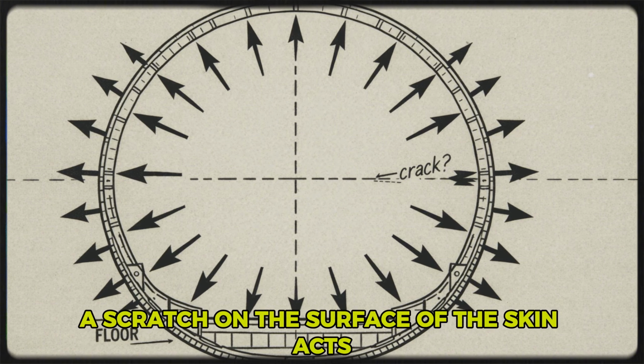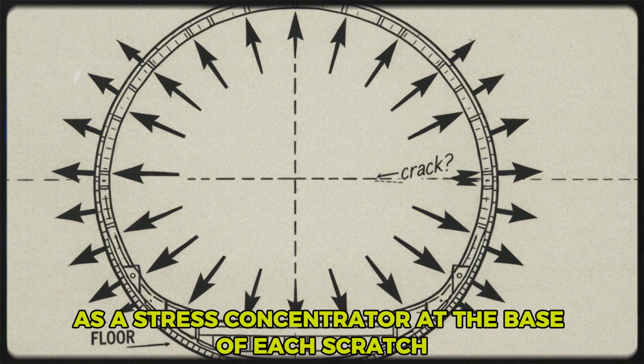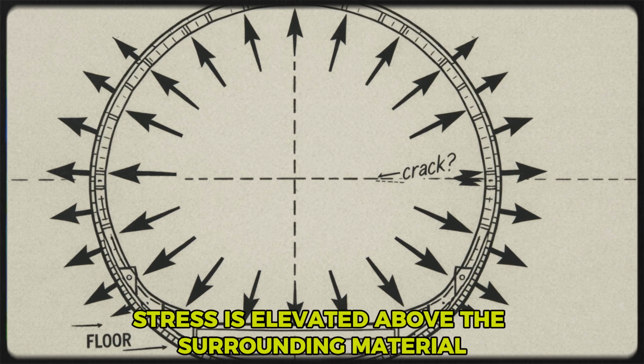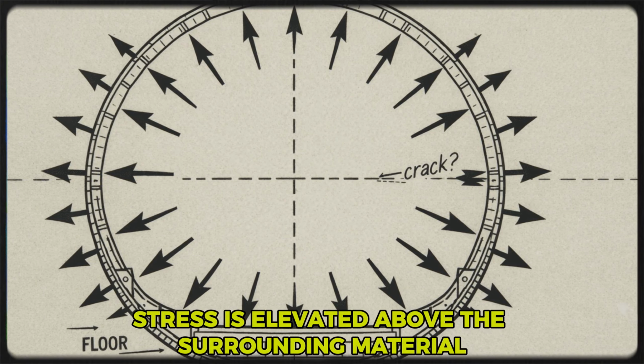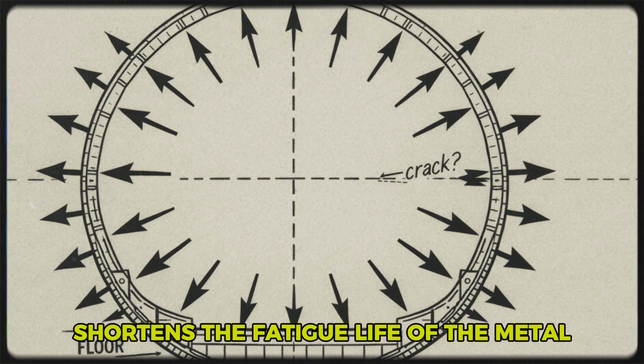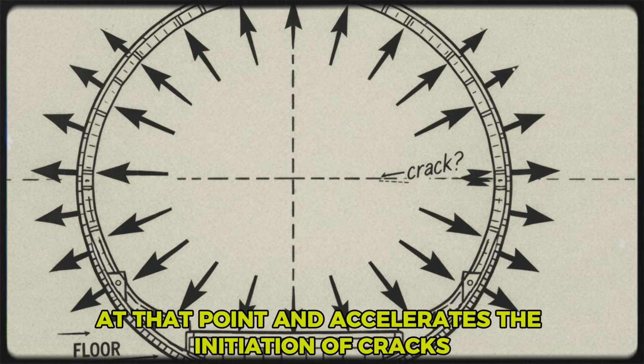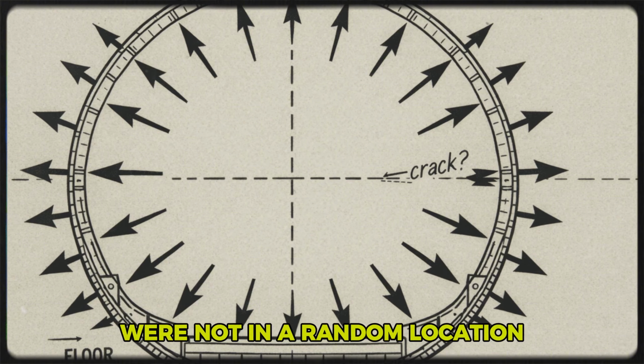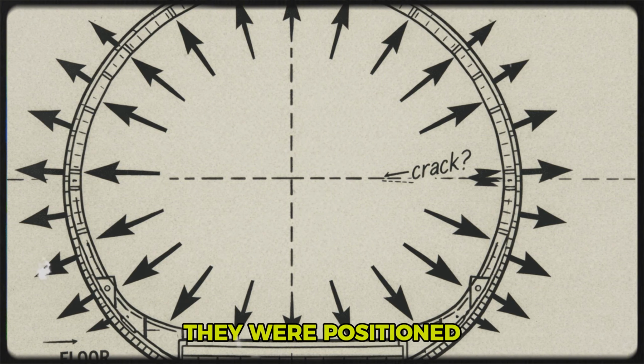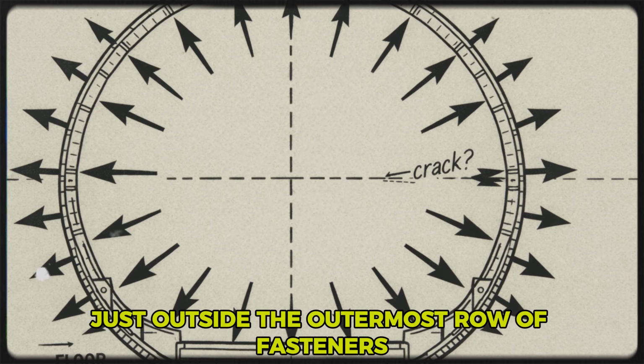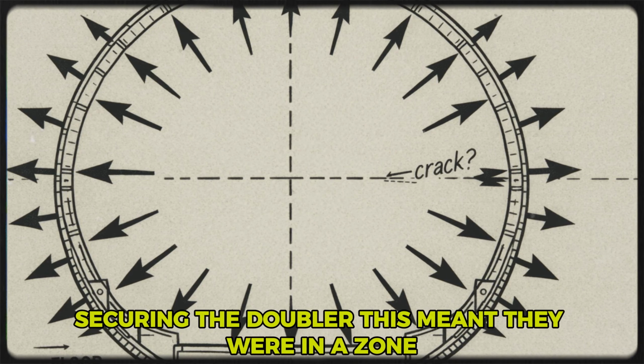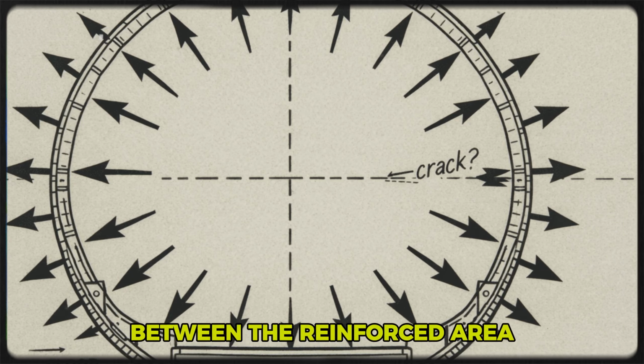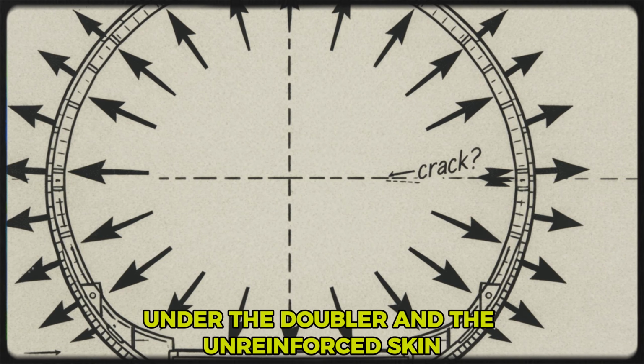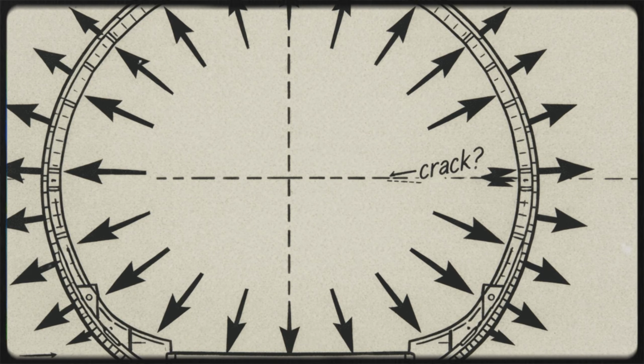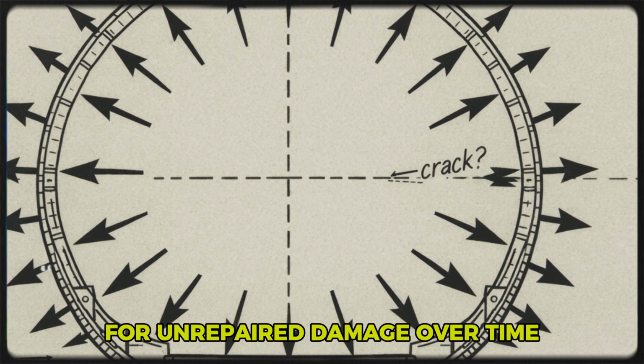A scratch on the surface of the skin acts as a stress concentrator. At the base of each scratch, local fatigue stress is elevated above the surrounding material. This elevated stress shortens the fatigue life of the metal at that point and accelerates the initiation of cracks. The scratches on B-18255 were not in a random location. They were positioned just outside the outermost row of fasteners securing the doubler. This meant they were in a zone where the load transition between the reinforced area under the doubler and the unreinforced skin created the highest stress gradients. It was the worst possible location for unrepaired damage.